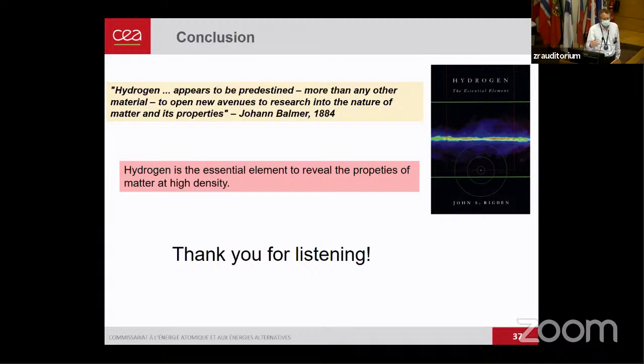Now, your question: the work of Marvin Cohen on this structural change, not topological in the sense that the Fermi energy is going to open a small direct gap, has been predicted. Then when you increase pressure, it's a little metal in this case, with a direct gap, and the density of carriers is going to increase with pressure. So the way to resolve that is really to do the reflectivity measurement, or to go to higher pressure and reach the atomic metallic phase. The other comment is that for the other claims of semi-metal, they involve a very small number of carriers.